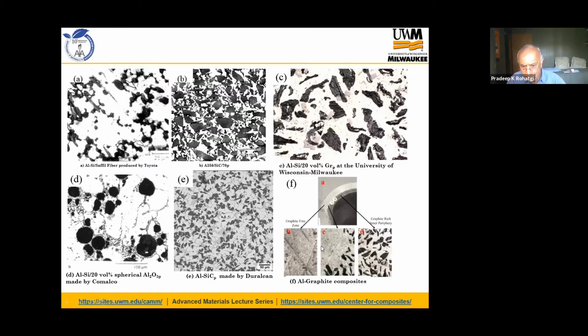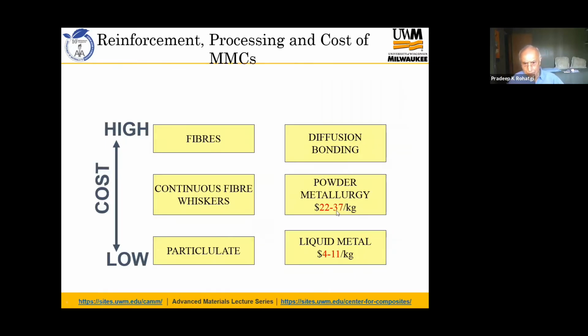And this slide shows a variation of aluminum graphite composite, how in a single step you can produce a functionally gradient composite. So what we did, we took a melt of aluminum graphite, centrifugally cast it, so all the lighter graphite particles come to the inner periphery, and this is where it can be used for a cylinder liner or bearing application. So it is a functionally gradient composite made by a very simple metal casting technique in a single step. And you can use this kind of technique to produce many other functionally gradient composites.